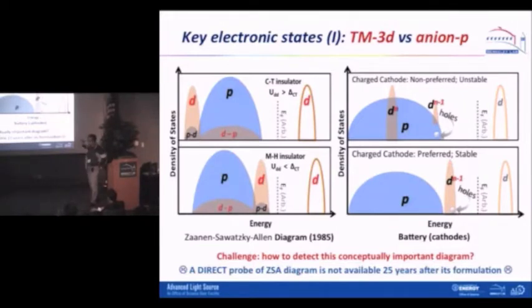If it's majority D, that's what you are hoping when you have charge and discharge, you have electron holes going into this cathode material. You are all changing this transition metal valence instead of changing anything else. However, if this is majority P, you will introduce this hole into your oxygen or sulfur, those anions. The result is you form this oxygen 1 minus, it will release oxygen into the flammable electrolyte. So when you inject oxygen into your flammable electrolyte in a car battery, it will explode.